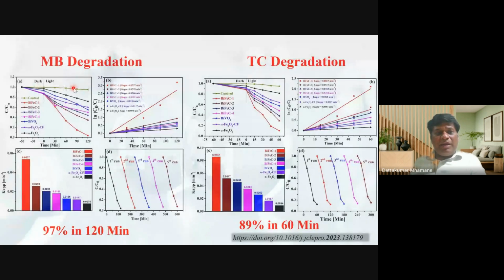There is no degradation of dye when we haven't added catalyst. So we added our catalyst, this red color, BIFEC, and you can see that within 120 minutes, over 97% of the dye is degraded. And here the tetracycline drug. This is also very dangerous because it contains chromium 6, which is hazardous. So chromium 6 is converted to chromium 3 with the help of our catalyst. This is the BiVO4 Fe2O3 carbon fiber catalyst.